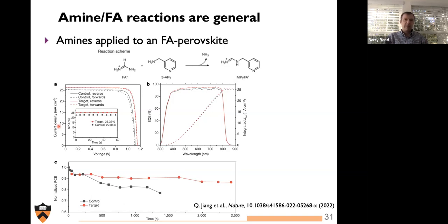In this case, it's not a simple proton reaction, but it's this addition elimination reaction, whereby in this case you're forming this cation and eliminating ammonia, which comes off as a gas. This cation is somewhat similar to the imidazolium cations that have been used, the BMIM cations that have been used in literature. And interesting analogies can be shown there. The nice thing about this work, and I think what makes it quite elegant, is that this is a terminal reaction. It only happens on the surface and it doesn't propagate farther. Exposure of some primary amine to an ammonium, like a methylammonium perovskite, will not be surface terminating. It will continue to propagate through the bulk, and you can essentially convert the entire 3D film to 2D if you're not careful and let it go too far.